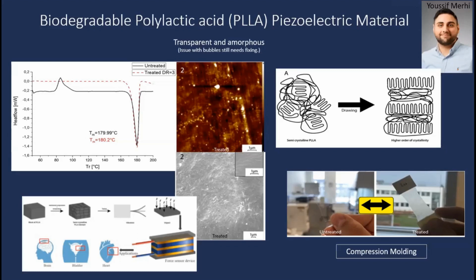And the way we are doing it is by compression molding. So we are trying to use heat and pressure, no chemical formula here, and trying to use compression molding to change the architecture of this PLLA. And we have shown that by changing the architecture, just by this compression molding, we are able to create or increase the piezoelectric response of this particular material. So again, these are unpublished results, we are still investigating how and why, but we have some fantastic results here. And again, the moment you mold it, it's good to go. You don't have to do any poling to get a sensing property out of it.